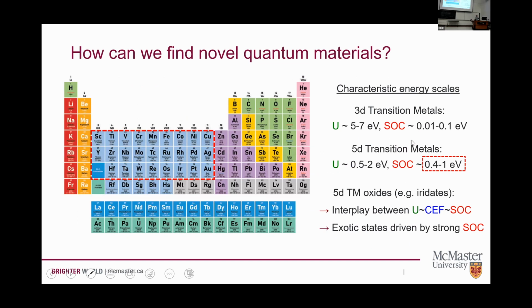Okay. Another strategy that we can use is to look at different regions of the periodic table that are maybe less explored. And so the materials that I'm going to focus on today are 5D transition metal oxides, and particularly 5D transition metal oxides based on iridium. So one of the things that's interesting about iridium is that because it's a heavy transition metal oxide, it has a very different set of characteristic energies than some of the lighter transition metals that we see more often, your irons, your cobalts, your nickels, your coppers.